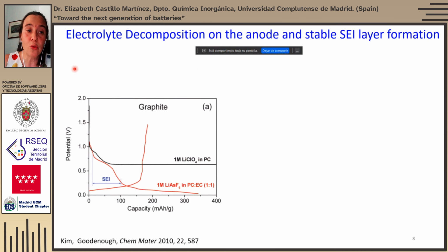So, we said that these batteries had an electrolyte in which ions move. And actually for lithium-ion batteries, this electrolyte is composed of a lithium salt, lithium perchlorate, or lithium hexafluoroarsenate, or lithium hexafluorophosphate, the most common case, in a mixture of carbonate solvents, propylene carbonate or ethylene carbonate. What you can see here is that this electrolyte is actually thermodynamically unstable at the very low voltage at which lithium is inserted into graphite, and therefore there is a continuous decomposition of the electrolyte. The addition of ethylene carbonate to the electrolyte mixture promotes the formation of a passivation layer on top of the material that allows the voltage to continue going down and the lithium ions to insert into graphite, and this becomes reversible.